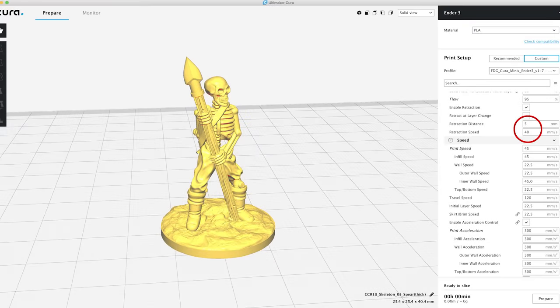All right, final thing I want to touch on very briefly is retraction. My settings for my Ender 3, I'm using 5 millimeters retraction distance with a speed of 40 millimeters per second. I'm going to go into a separate video later on with a lot more detail on retraction. I don't want to spend that much time on it here, but just very briefly, if your retraction distance is set too large, you're retracting and feeding the same section of filament more times in cases where you have a lot of tight detail with a lot of retractions.